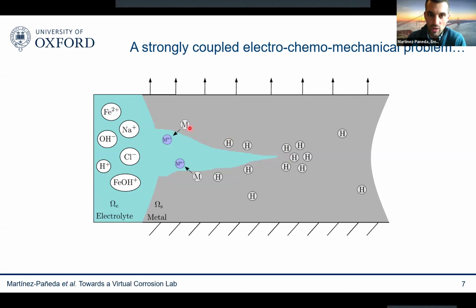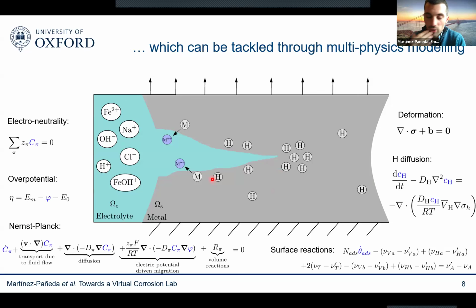You have, for example, corrosion, so you have metal atoms detaching. You also have other chemical reactions that induce the absorption of dangerous species such as hydrogen. Then those hydrogen atoms will travel inside the metal. They will be attracted to areas of high hydrostatic stress. They will lead to damage, and then you'll get the fracture of the component, and so on and so forth. So there are many electrochemomechanical phenomena happening here. All of them are important, and all of them are strongly coupled. So if you really want to capture the mesoscale physics of the problem, you need to capture all these phenomena. And the good news is that we know what the PDEs are that describe each of these physical phenomena.